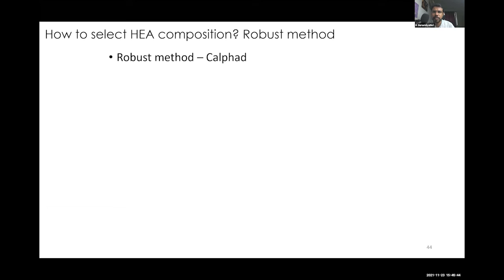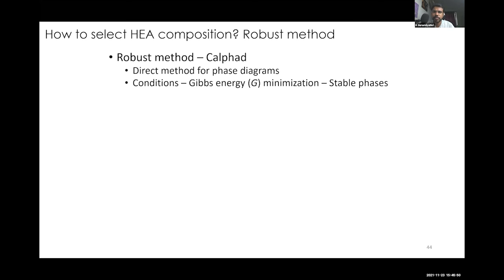The robust method is CALPHAD, which is my research area. It's the direct method for making phase diagrams. So conditions we have to give, like composition, temperature, pressure, things like that. Then we can do something called Gibbs energy minimization. Whichever phase or combination of phases have the lowest Gibbs energy, those will be the stable phases. So there is no question of increasing the configurational entropy and stabilizing only solid solutions, because even intermetallic phases can have certain increase in configurational entropy. So it's not a simple thing. Gibbs energy is the only parameter we should rely on, which takes into account enthalpy also, not only configurational entropy.